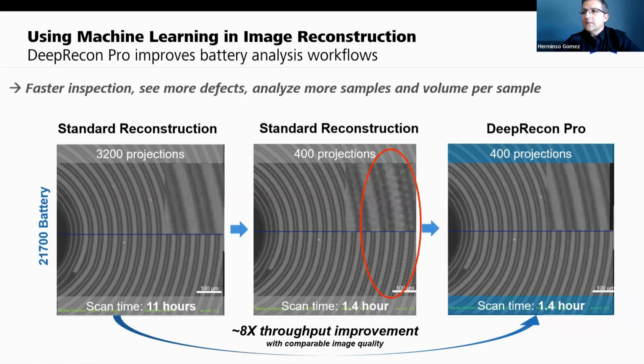This is a very high resolution scan of a 21700 battery with over 3,000 projections. Very long scan. If you start trying to cut corners with the traditional way of reconstructing, then the problem is you start seeing this type of defects or artifacts. They are not real. They are created by the fact that you use an analytical algorithm and you cut the projections. So it's very hard to cut corners with standard reconstruction.